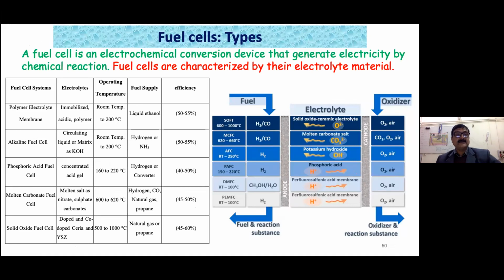Again, you see this simple chart showing the operating temperature, and you see the efficiency, very nice efficiency you are getting in comparison to the solar cells. They are up to 50% and 60% in the case of solid oxide fuel cells. So you see what fuels you apply, the fuel reaction substance, and then the electrolytes which you are using for, let us say, the solid oxide cell. The electrolytes are, as I said, doped and co-doped ceria, and molten carbonate, the molten salt. So you see that these are the different electrolytes.